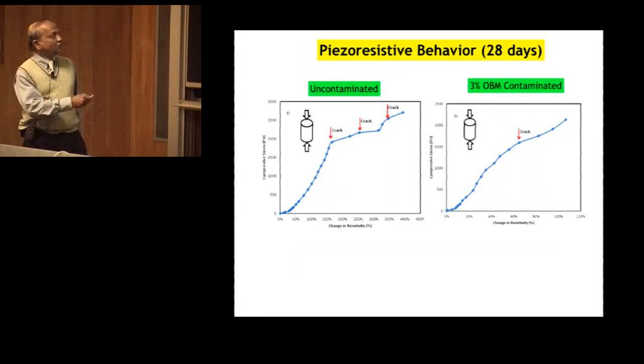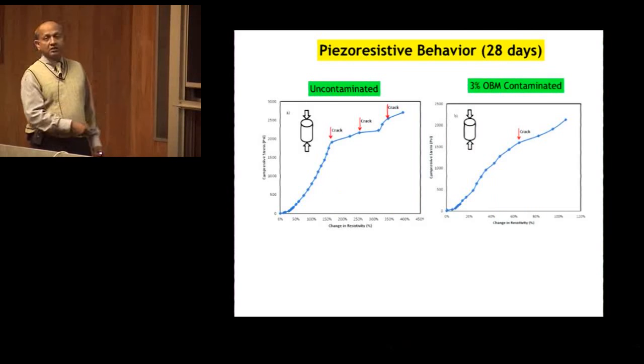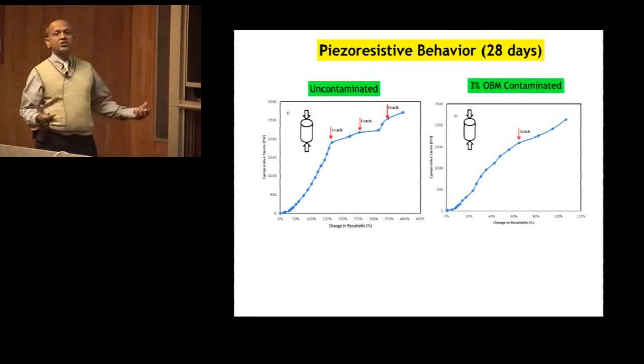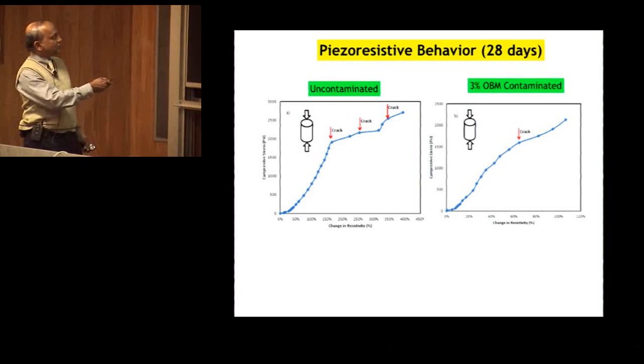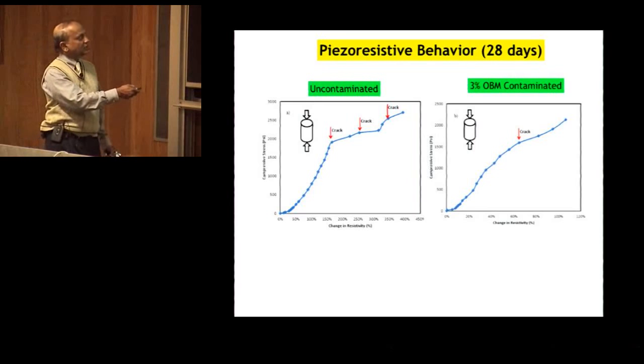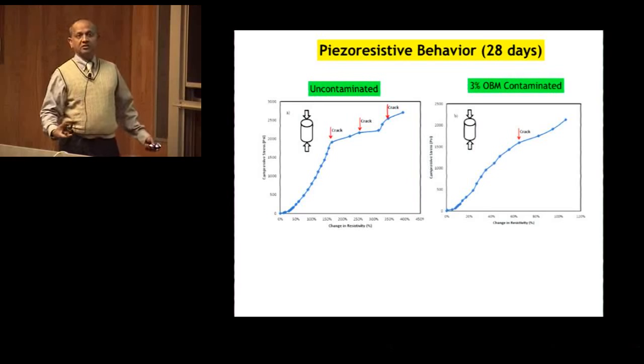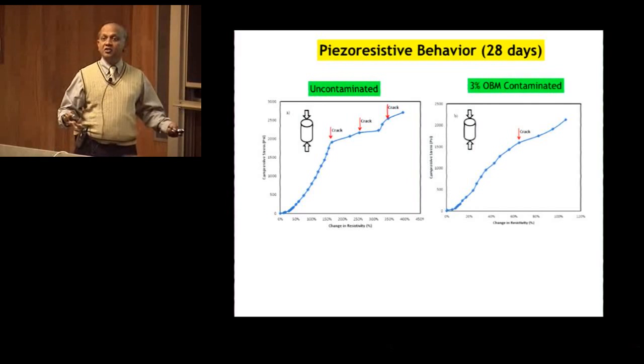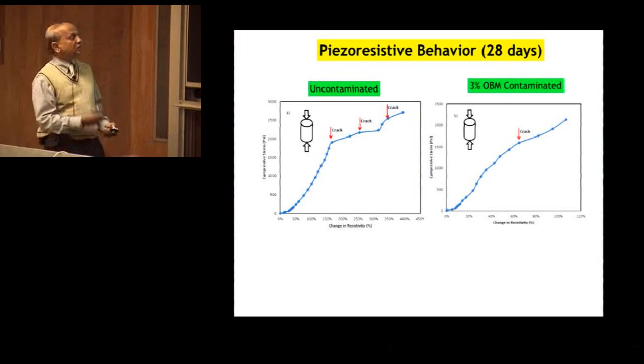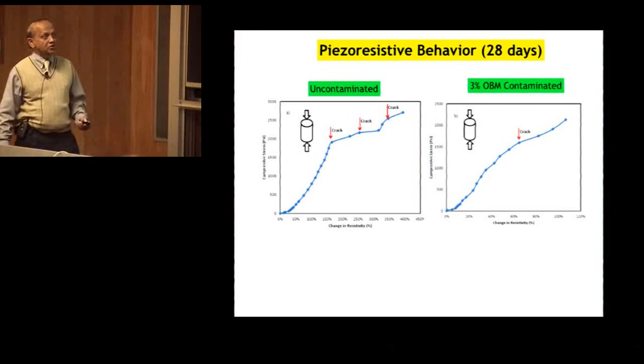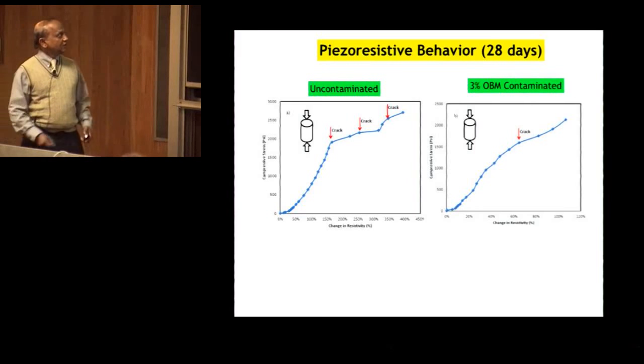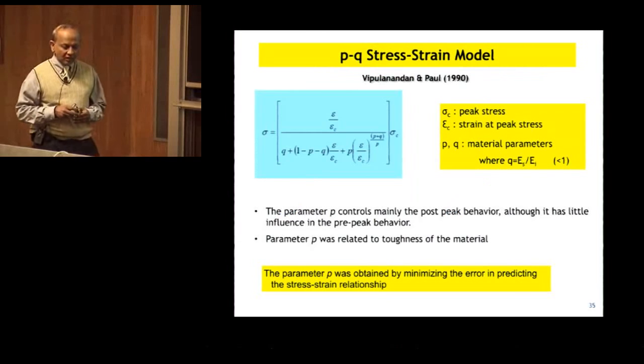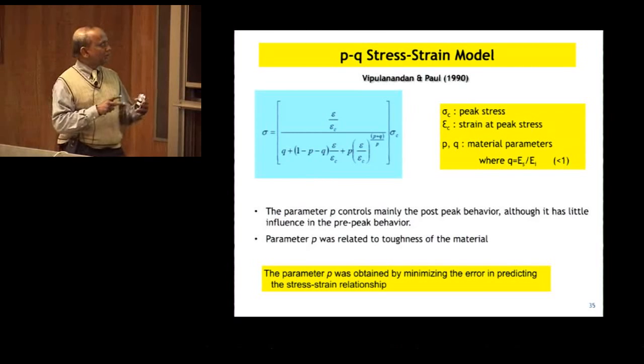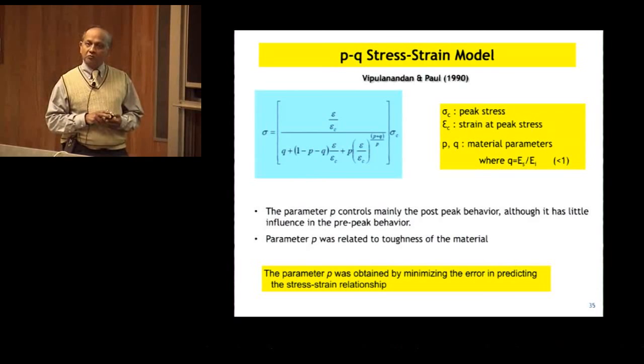Also, I just want to show you that when the cement gets contaminated, it also affects the piezoresistivity. For instance, you saw the cement without contamination shows very, very high changes in resistivity with loading. But when it is contaminated, the change in resistivity is also affected, because there is oil in the cement. And this also will tell you that your cement is contaminated from the changes you measure. So this is what it is. Then I just want to touch on a few things in addition to this. Basically, we also do a lot of modeling.